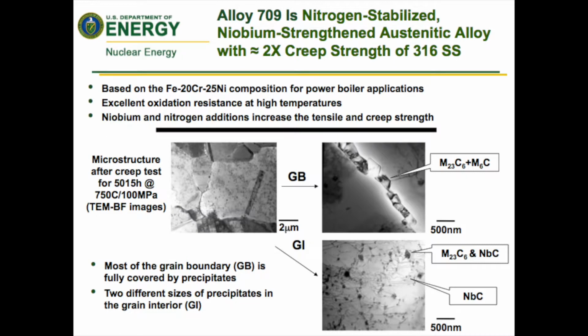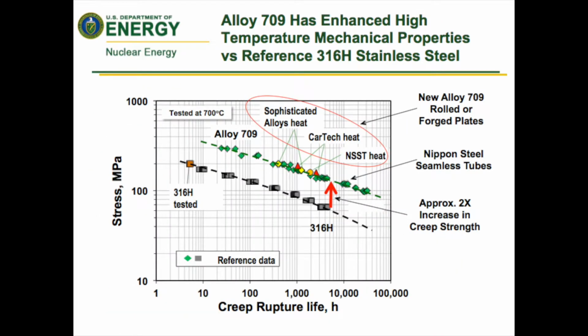And you can see that they still display a very nice coverage of precipitates both in the matrix and in the grain boundary, which provide for strengthening of this material without undue embrittlement of the material. We're very pleased with the way this material looks heretofore, but we don't have all the answers for it yet. We have done a lot of preliminary testing on it, and we have clearly shown that it does have the enhanced high temperature mechanical properties we're looking for.